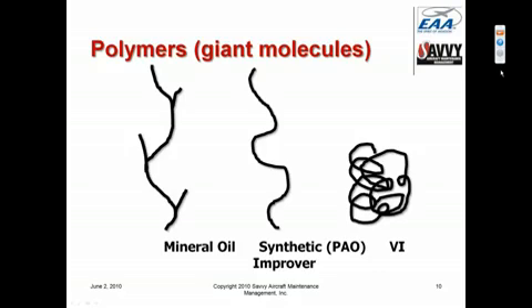The other characteristic about mineral oil versus synthetic is that mineral oil is much better at holding particulate material in suspension, again, because of its branchy nature. Its ability to do that degrades over time as it remains in service. But if we change the mineral oil fairly frequently, it does a pretty good job of keeping the engine clean, holding particulate matter in suspension, that particulate matter that's too small to be caught by the oil filter, and allowing us to drain out the junk at oil change time, rather than having it settle out in the form of sludge on the inside of the engine.